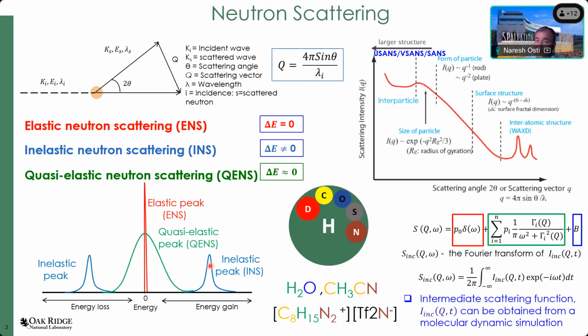This quasi-elastic peak, or the quasi-elastic neutron scattering, directly depends upon the incoherent neutron scattering cross-section of the element. As you can see here, hydrogen has a very high incoherent neutron scattering cross-section. Therefore, this technique is highly applicable to resolve the dynamics of hydrogen-containing material, for example, water or some organic solvent. Here I have listed acetonitrile and ionic liquid, which has hydrogen only in the cation.